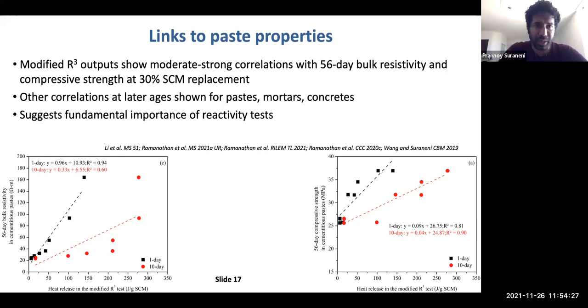We've shown a lot of other correlations as well with pastes, mortars, and concretes, with strength, with calcium hydroxide consumption, with bound water, etc. Now, it's not difficult to show correlations, but the problem is it really depends on the conditions. First, you want to do this at later ages. You want to do this with adequate SCMs because otherwise filler effects dominate. And the most important thing is that it's not necessarily going to be a 1:1 correlation, because reactivity is essentially a pretty complex thing. There are a lot of other factors that affect cement-based or concrete property development.